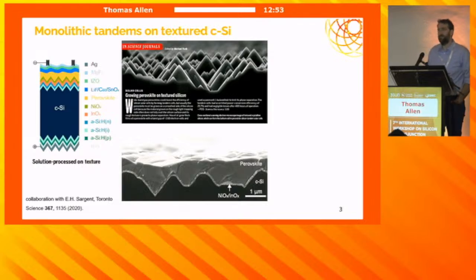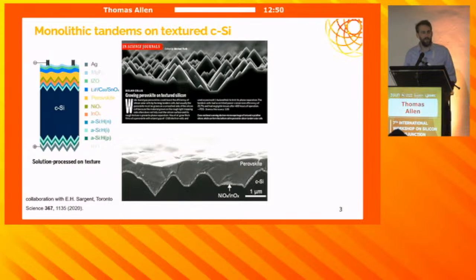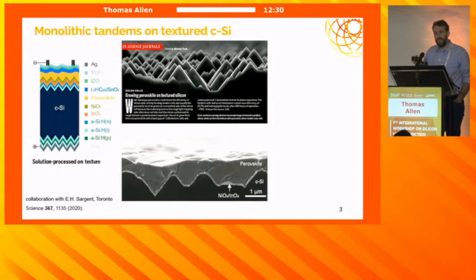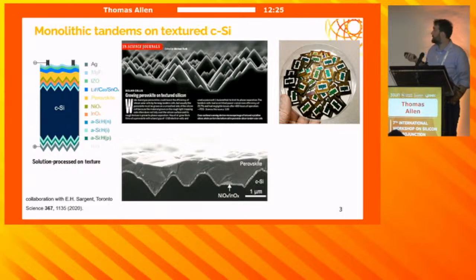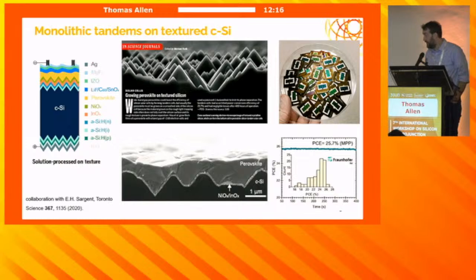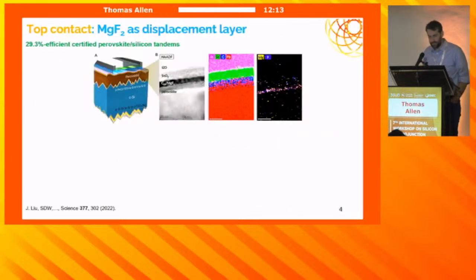And just in general, the perovskite structures that we've all landed upon are in the PIN configuration, meaning that the silicon, at least we're working on silicon heterojunction cells, has the P layer at the back, the N, which is typically nanocrystalline silicon in our case, at the top, and then the perovskite has the HTL, the perovskite, and then the ETL at the top. Okay, so these were the first generation of cells, and despite the fact that I said optically they're very good, you can tell that optically they were pretty bad at the start, but we were still able to achieve an efficiency around 26%.